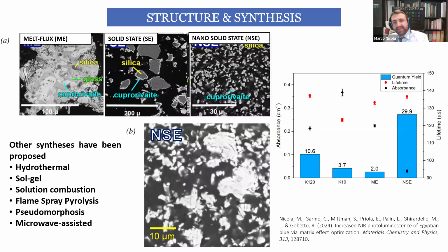Obviously, it is also possible that they put in silica, a source of calcium, like lime, for instance, a source of copper, and a flux that normally contains potassium or sodium. So we have those two possibilities. Probably there was also a difference over time. Maybe at the very beginning they used fluxes mainly based on potassium, maybe from ashes. And then when glass technology arrived, 2000 years later in comparison with Egyptian blue, they started to use sodium-containing fluxes like natron. Natron is a very important material for those applications, and was a key material for many thousand years for the production of Egyptian blue.